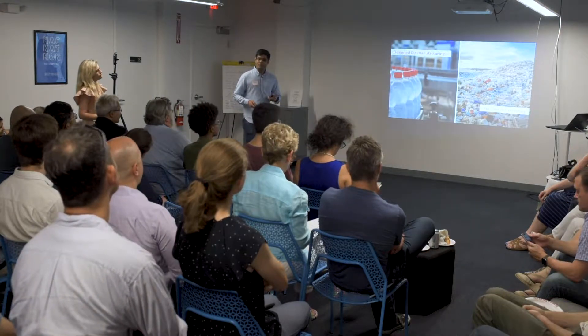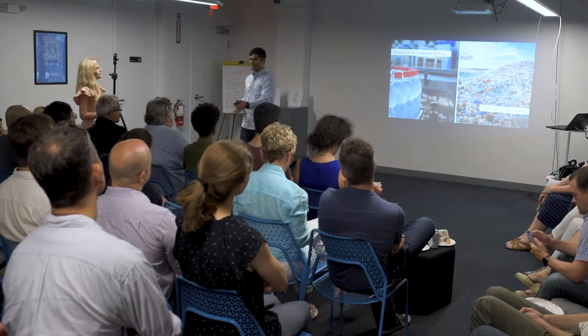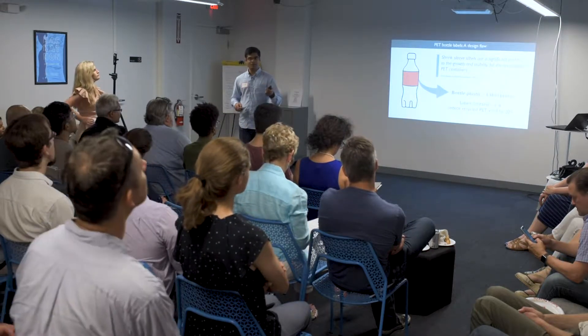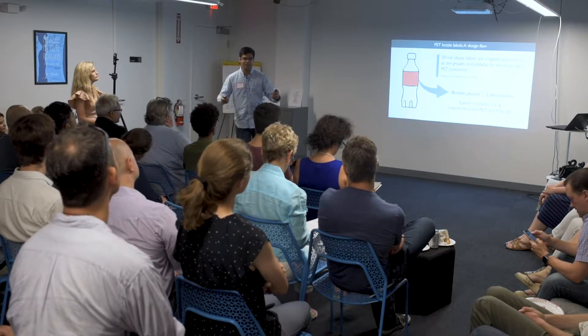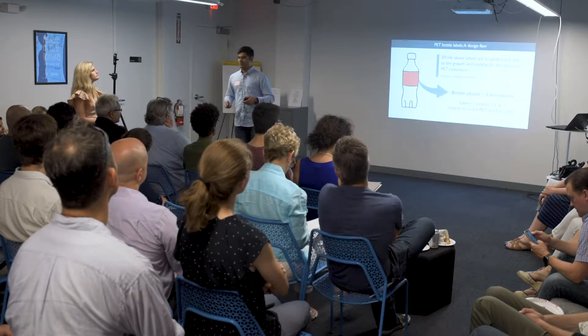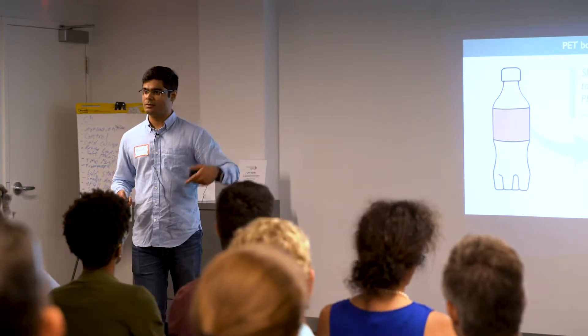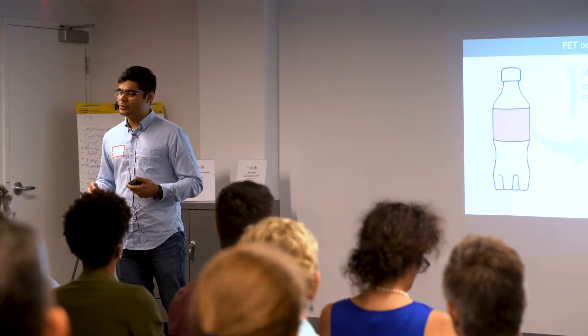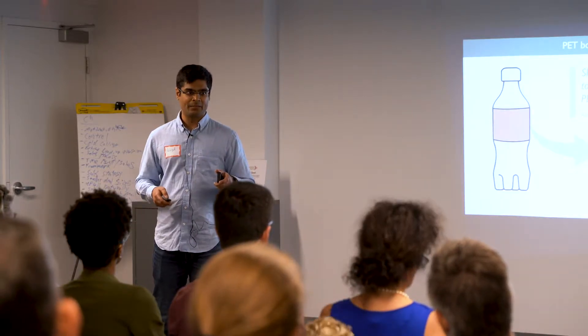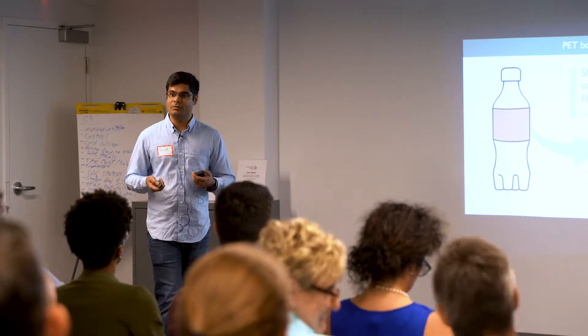But the underlying problem of plastic packaging leaking into our environments has not really gone away. The big problem with plastic packaging, or packaging for that matter, is that it's designed for manufacturing but not for recycling. Take a simple plastic bottle as an example. The bottle that you're drinking water or beverages out of typically has a label made of a different plastic type than the bottle itself, which means the recycler has to separate the label away from the bottle. Sounds simple, but it's extremely complicated. Labels are the largest contaminant in bottle recycling — they reduce bottle recycling yields by about 25% and account for almost 10 to 12% of cost.